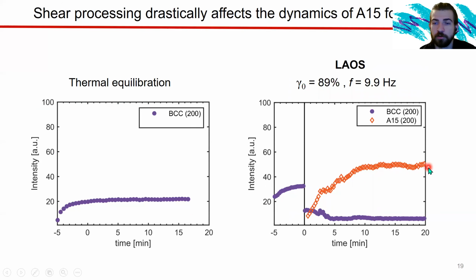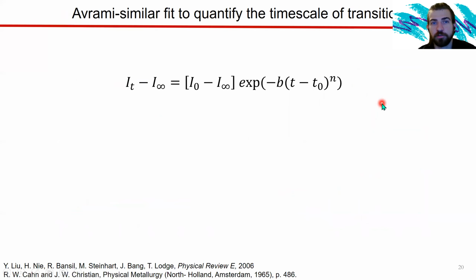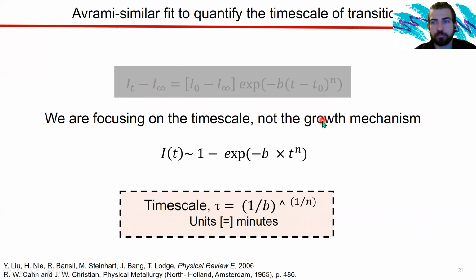Now this is under different oscillation conditions. So how are we going to compare them? Well, we're going to apply an Avrami type fit, the Johnson-Mehl-Avrami equation, where you take your intensity and you fit it to the stretched exponential, where you have 2 parameters, b and n. Now, if you zoom out, this is basically just a stretched exponential fit, and we're just focusing on pulling out a time scale using this fit.